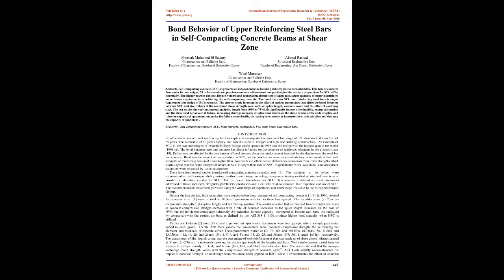The current study investigates the effect of various parameters that affect the bond behavior between SCC and steel rebars at the maximum shear strength zone, such as splice length, concrete cover, and the effect of confining steel. The test results showed that increasing splice length from 50% to 75% LD significantly improved the ductility, energy absorption, and the structural behavior at failure.